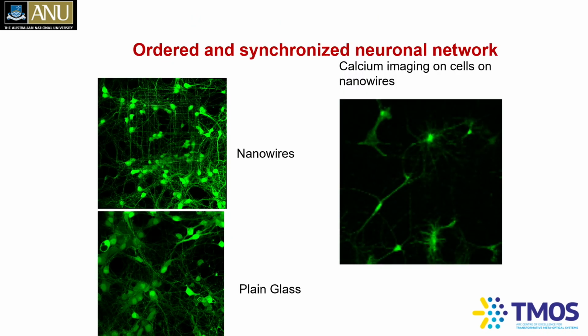As Mike in his talk was saying about action potentials and how the neuronal signals are measured, what we do in this case is that Vinnie puts in some calcium dye. And then whenever action potentials are fired by these neurons, calcium ions pass through the neuronal ion channels, and the fluorescent intensity of the dye changes. And then we take this video and make correlation maps of what will happen if this neuron is firing, what's happening to this neuron and this neuron, these astrocytes, and she creates correlation maps. And then we compare these neurons grown on nanowires with the neurons grown on plain glass substrates, because that's what neuroscientists typically use.